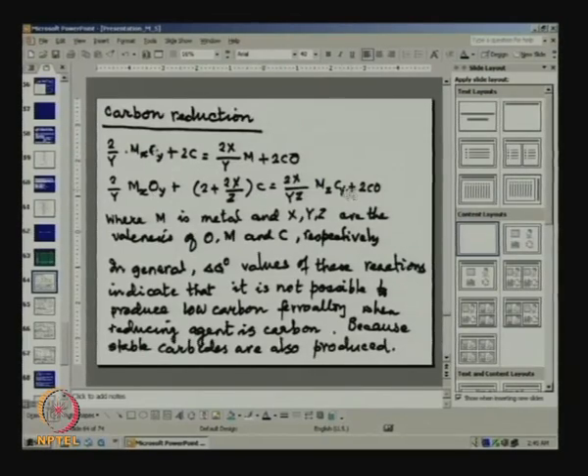It can also produce metal carbide. MxOy reduced by carbon produces metal, or MxOy reduced by carbon can also produce MxCy. So, we have to see which reaction is going to predominate. Now, in general, the delta G naught values of these reactions indicate that it is not possible to produce low carbon ferroalloy when the reducing agent is carbon, because stable carbides are also produced. It will not be all carbide, it will not be all metal, it will produce metal with substantial amounts of carbides. So, carbon reduction would always do that.